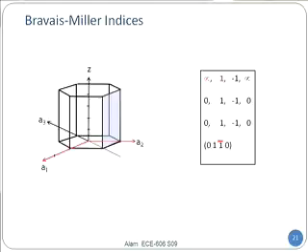And check that out. But one thing you should notice, if you haven't already, is that if you have done your math correctly during the exam, this is a good way to check things. If you have done your math correctly, then the first 3 must always sum to 0. You can see 0, 1, -1. So 1 and -1 gives you 0.